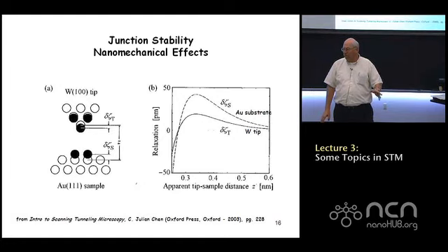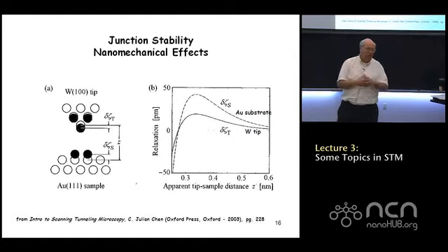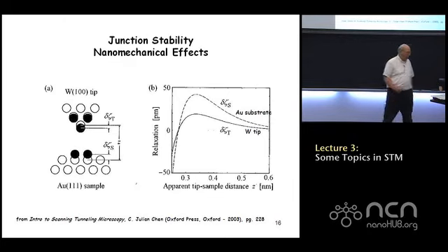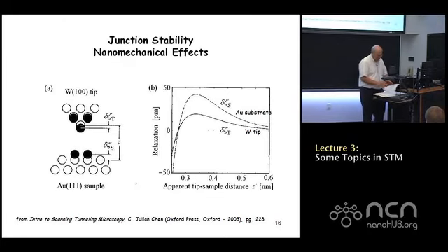But the forces between the tip and the substrate are significant, and they can cause tens of picometers of deformation. Easily tens of picometers of separation between, let's say, a tungsten tip and a gold substrate. So that's something you've got to remember, especially when we start to talk about AFM in another week. That sets the scale for the deformations that could occur.